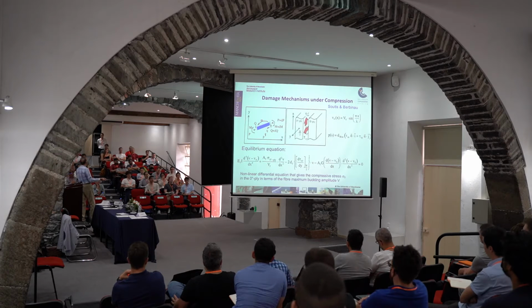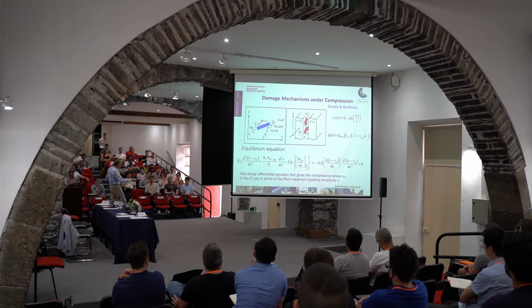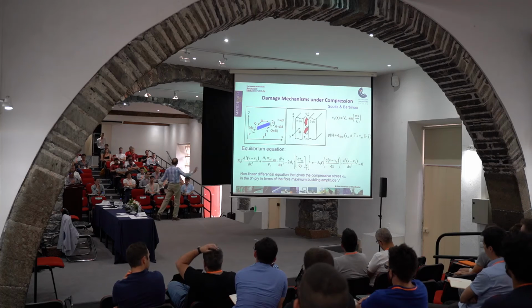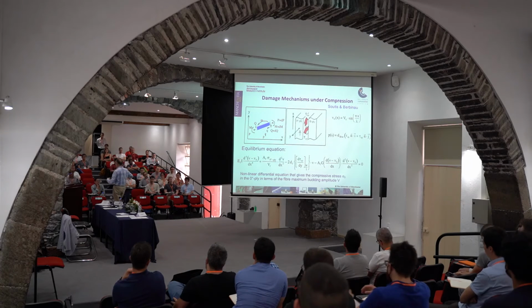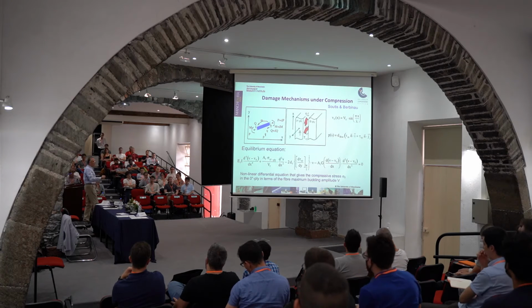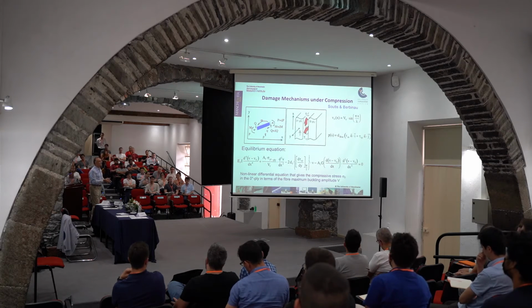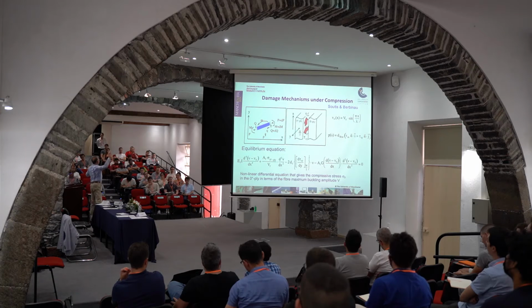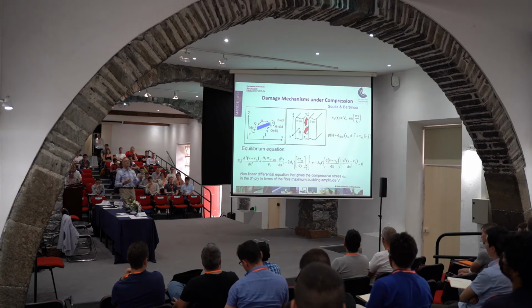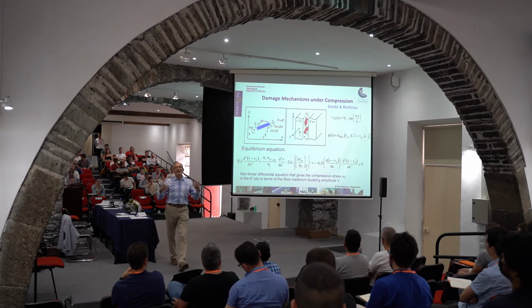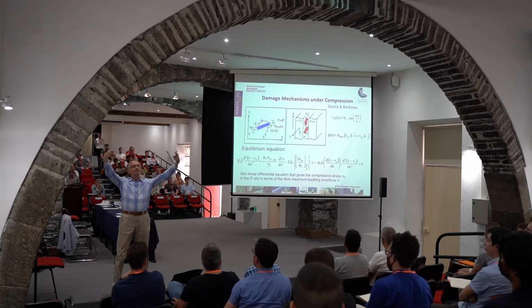This equation is the Timoshenko beam on an elastic foundation. Timoshenko took the equation to solve the problem for a beam on elastic springs. This is now using the same principles. It is the Timoshenko beam theory, but on a non-elastic foundation, because as you can see, the shear modulus G of the material varies with applied load, applied displacement. So V is the applied displacement introduced by that compressive load. And V naught is the initial fiber imperfection, fiber misalignment, fiber waviness, which again, you need to detect non-destructively. Good luck, mate.